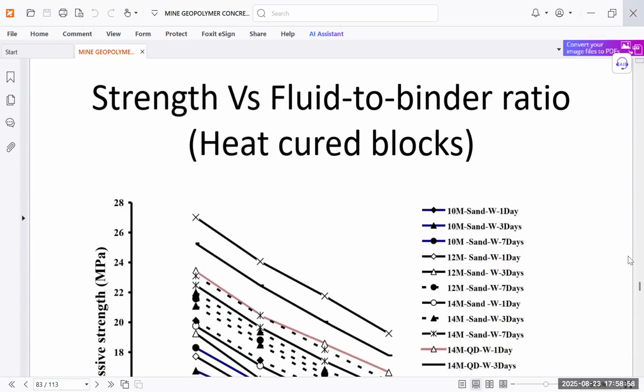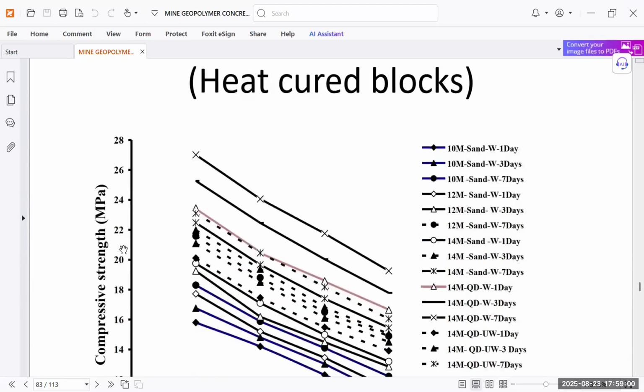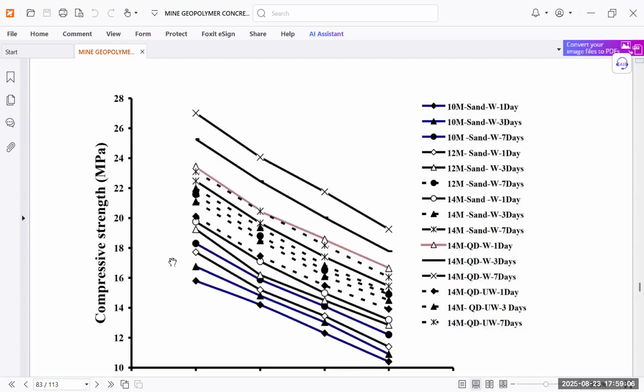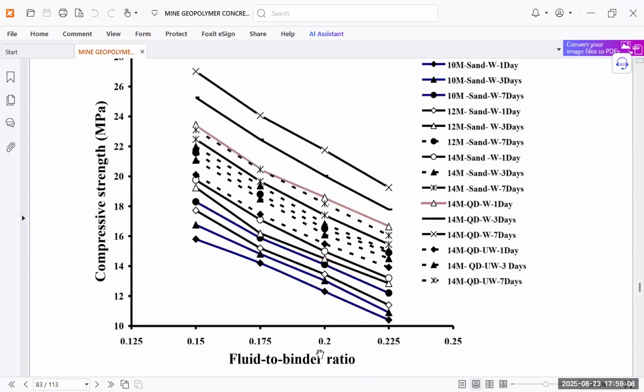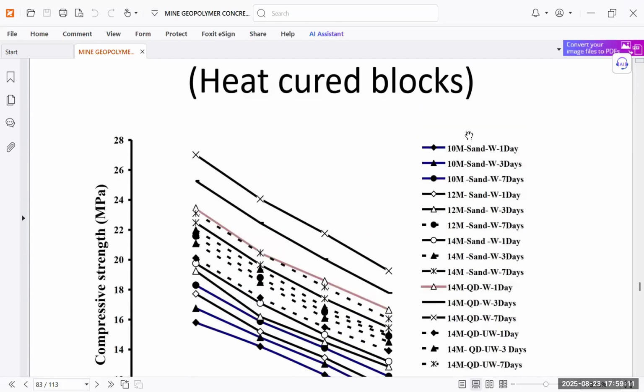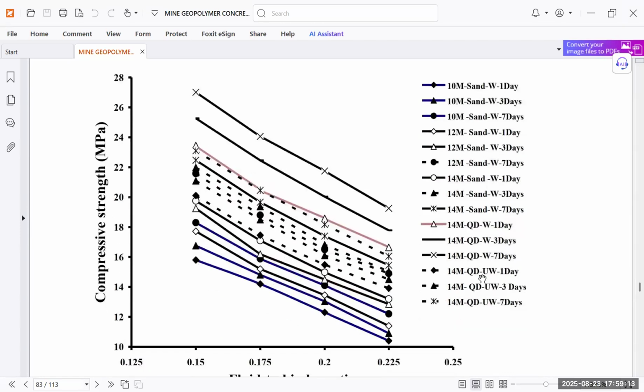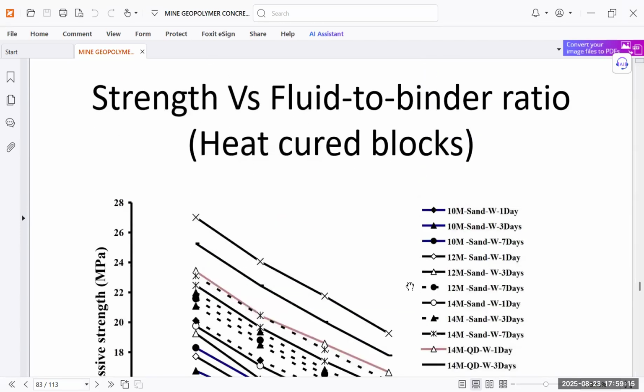In this case, we have seen heat cured blocks. You can see that compressive strength is there. This is the variation of compressive strength with fluid to binder ratio. Then, after this, the strength at different days is there. You can see this plot.